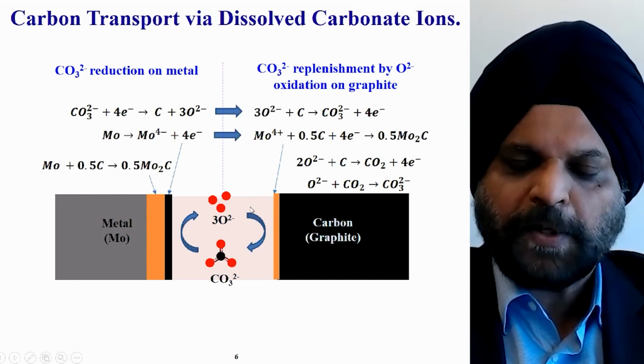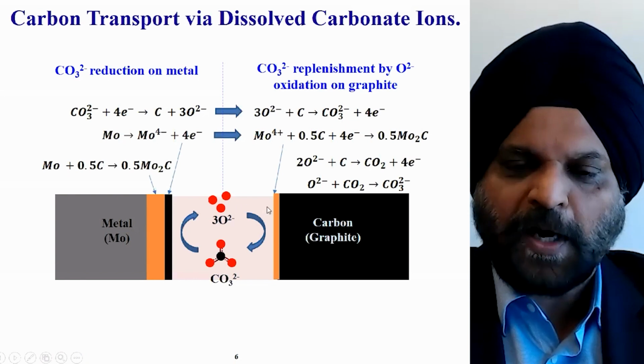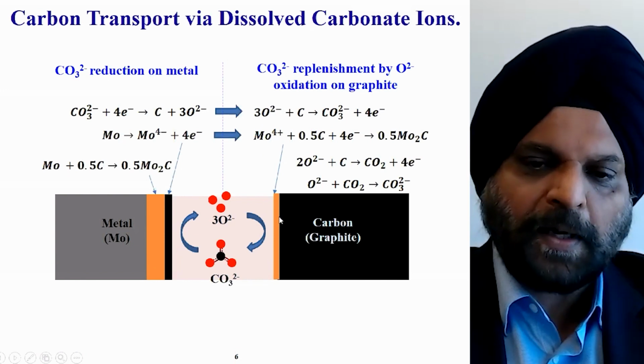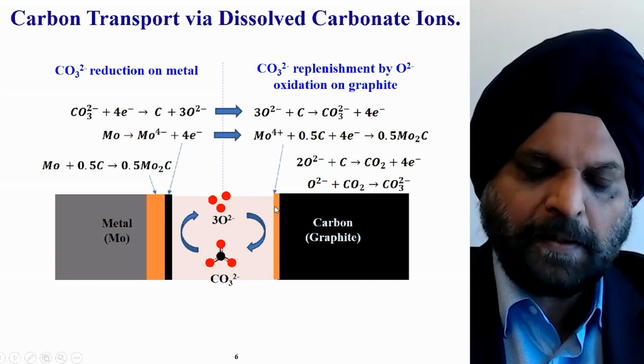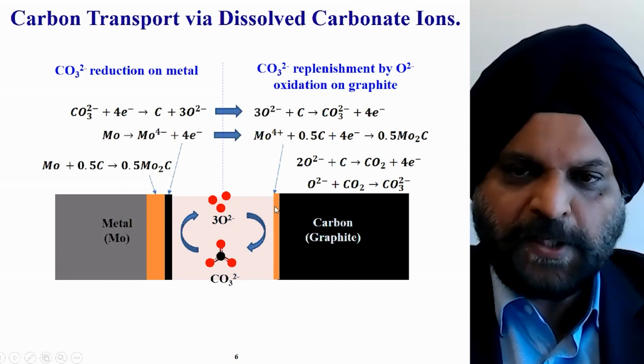Similarly, a reaction can occur where you have carbon already on the graphite surface. You can transfer these soluble metals onto the graphite surface and find that you now have metal carbides on the graphite surface as well.